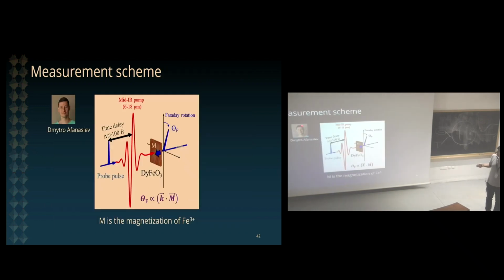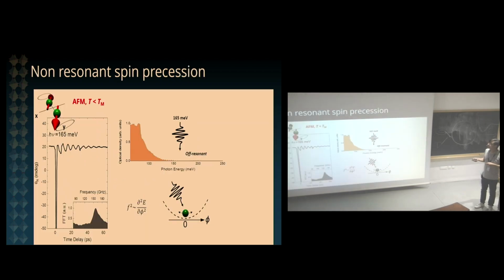For this reason, Dima has developed a pump probe setup in which we probe the magnetic properties by means of Faraday and Kerr rotation. In a Faraday experiment, you're using a probe pulse that is transmitted across your sample, and you track the rotation of the polarization of this pulse over time, in a time resolved fashion. In a Faraday rotation experiment, you are probing the component of the magnetization of your sample that is projected along the propagation direction of the light. Now I'm going to show you a series of measurements of the Faraday rotation. You can think of this as the magnetization component that is probed by the light versus time.